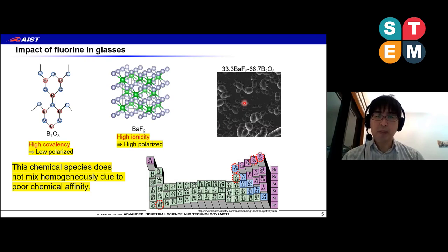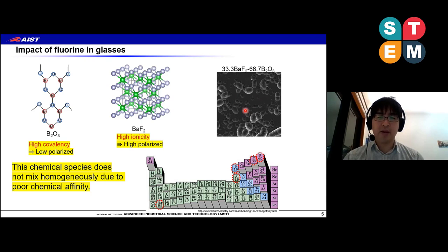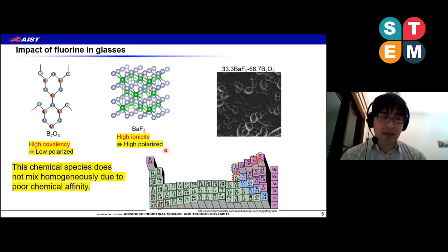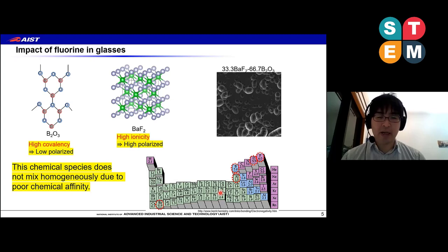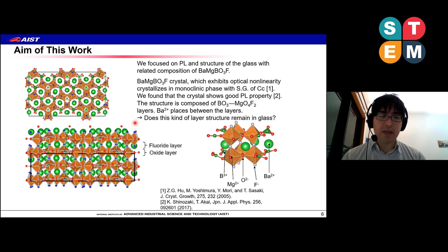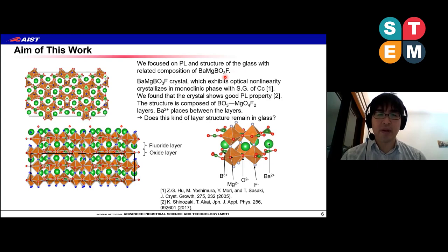This glass is composed of a covalent B2O3-rich matrix and fluoride-rich phase-separated domains. This is due to the less chemical affinity between them. When we add magnesium or aluminum species between the boron domains, this nanostructure changes and we can control the nanostructure. We focused on the photoluminescence and structure of a glass with composition based on BaMgBO3F. This is a crystal structure composed of a fluoride layer — the blue represents fluoride and the green dots represent barium ions.